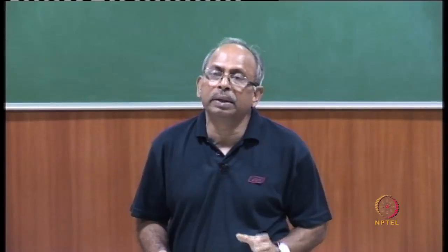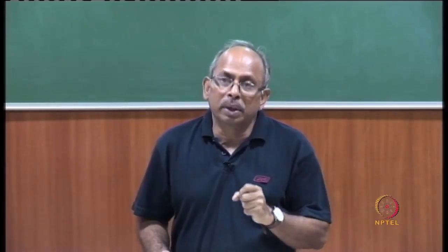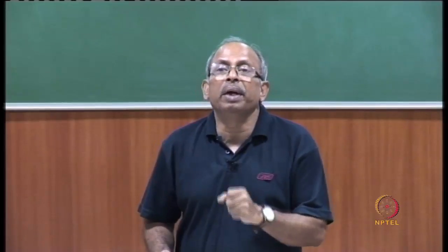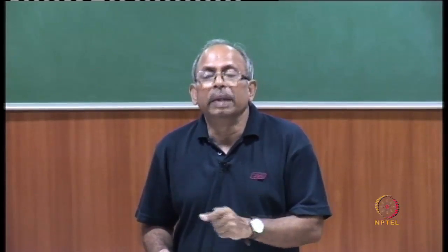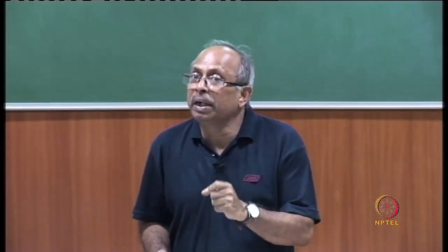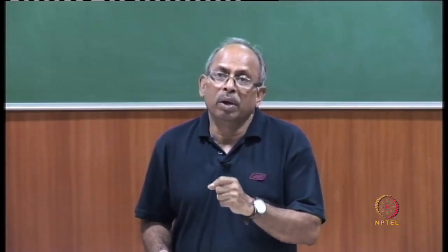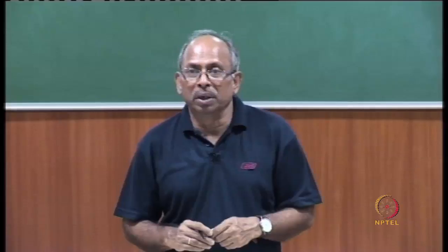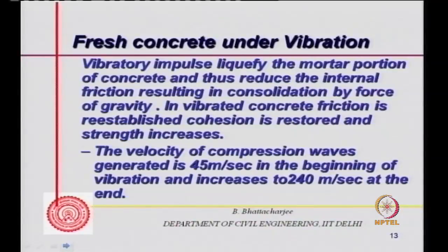Vibratory impulse essentially causes the water in the cementitious or paste system to vibrate, moving more than the solid particles. And the more constricted the necks are, the more pressure it will exert. This pressure overcomes the friction, resulting in a kind of collapse of the system. The velocity of compression waves generated could be of the order of around 45 meters per second in the beginning of vibration and increase to 240 meters per second at the end. So essentially liquefaction of the mortar occurs.